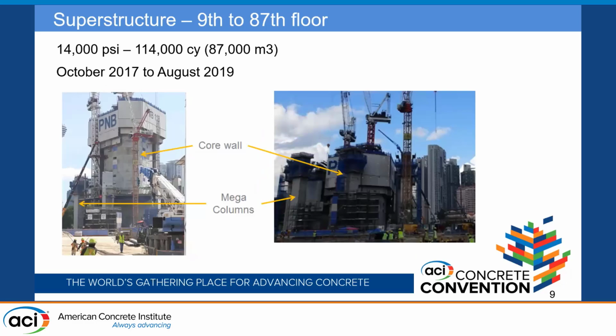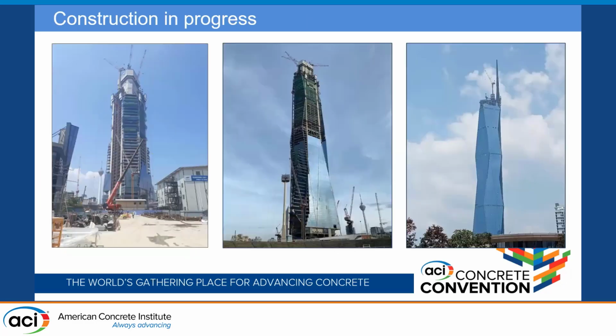14,000 PSI concrete, again, was used from the 9th floor to the 87th floor for the core wall and mega columns. And the formwork was a self-raising Doka platform with hydraulic jacks. The formwork was all steel, and placements were on a 5-day sequence between lift reinforcement and pouring the next lift. And this required 3-day high early strengths on these mixes to keep the formwork moving, which is also quite impressive when you have all the other restrictions that you're going through on this job.